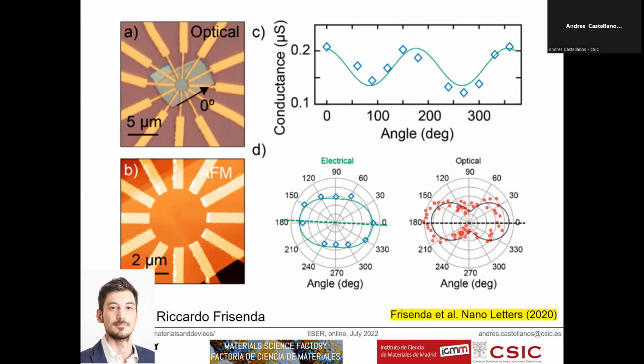But surprisingly enough, if you fabricate devices with this Franckeite flake with electrodes at different angles, and you measure the conductance along different directions, you see that the conductance fluctuates. Also the transmittance of these flakes fluctuates with the angle, and they are aligned on both axes. This is the absorbance. The absorbance gets larger along the direction of highest electrical conductance, very similar to what we have seen in titanium trisulfide.